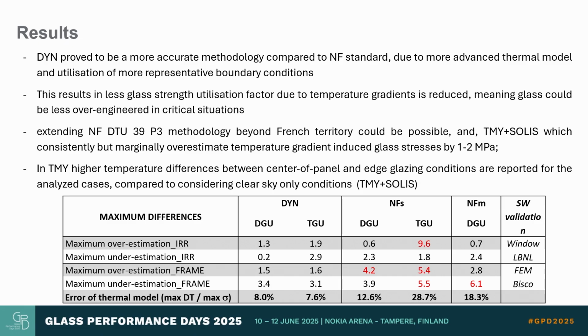Finally, in this table, what we try to do is to evaluate the error that you saw before in the utilization factor, which is simply the maximum error that we make on the delta T divided by the maximum strength of the glass that we can assume, as a comparison between our dynamic methodology and the national French standard, and divided between double and triple glazing unit. And what we can see is that compared to a more accurate calculation, the French NF standard basically could make errors that are much higher than 10% in terms of the utilization factor.